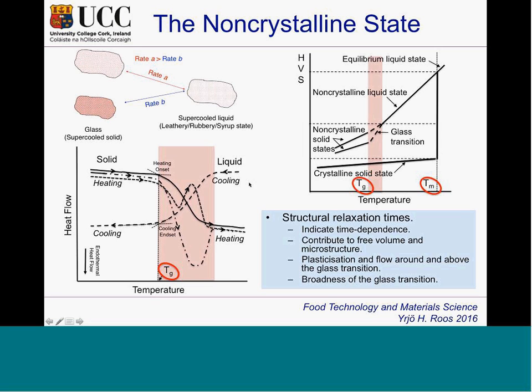If we have cooling and heating at the same rate, we probably have quite a nice glass transition, same heat capacity change over the temperature range that we call glass transition. That's then a material that we cool slowly and then heat rapidly. We will see that there is now an overshoot. And that's because in slow cooling, we allow the material to go to a fairly compact form. And the material is in the glassy state.